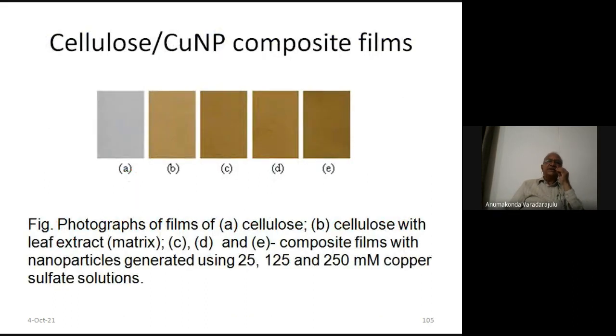But then we generated copper nanoparticles because silver is expensive. So we want to reduce the cost of this particular nanocomposite film. In a similar manner, we prepared the nanocomposite films with cellulose. This is the cellulose matrix, and these are the nanocomposite films prepared with copper sulfate source solutions of 25 millimoles, 125 millimoles, and then 250 millimoles. As the concentration is increasing, the color is also deepening, and the color change from the matrix to the nanocomposites preliminarily indicates the formation of these nanocomposite films.